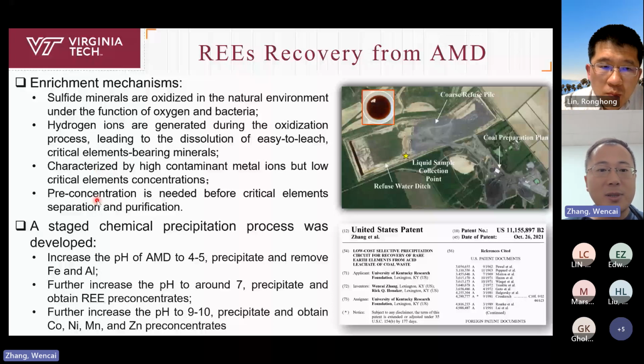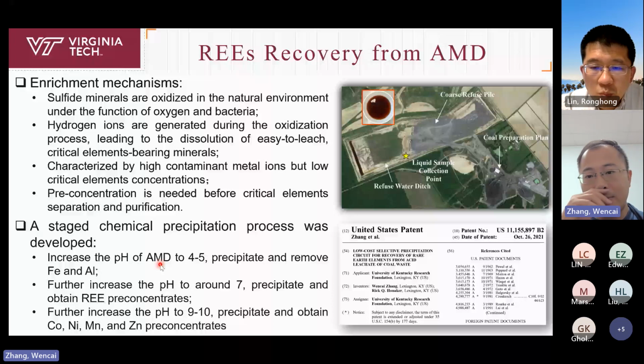So what we did is that we increased the pH of acid mine drainage to between 4 and 5. In this pH range, you can precipitate and remove iron and aluminum. And after that, you can do filtration. For the filtrate, you can further increase the pH value to around 7, and then you can precipitate and obtain rare earth preconcentrates. And if you further increase the pH value to 9 and 10, you can precipitate and obtain the preconcentrates of cobalt, nickel, manganese, and zinc. Okay, the concept is simple, but we got a patent awarded in terms of this technology.